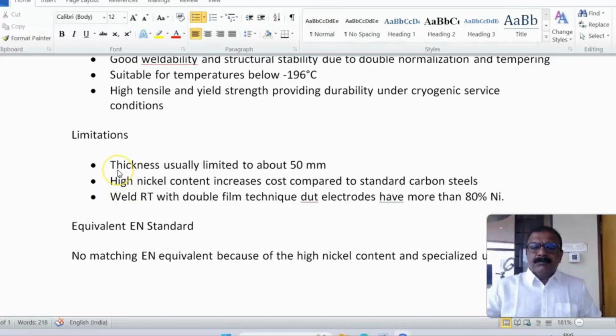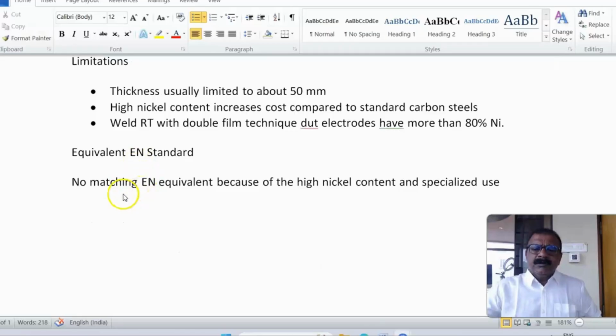Limitations of 9% nickel steel: thickness is usually limited to 50 mm. High nickel content increases the cost compared to standard carbon steels, and weld RT must be done with the double film technique because electrodes have more than 80% nickel, whereas the plate is only 9%, so we have to use double film. As for an equivalent EN standard, there is no matching EN equivalent because of the high nickel content and specialized use. Now we will see the requirements of SA 353.